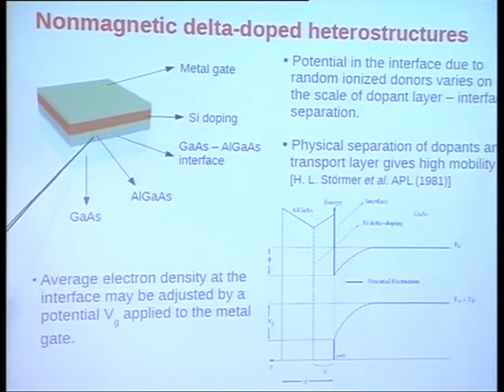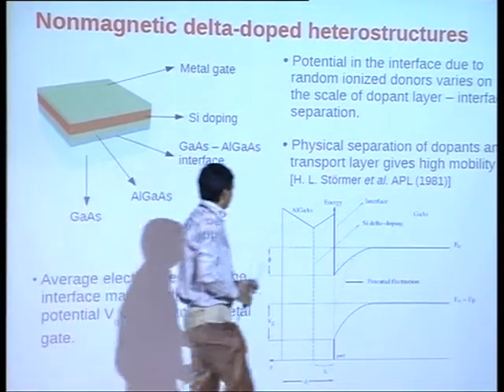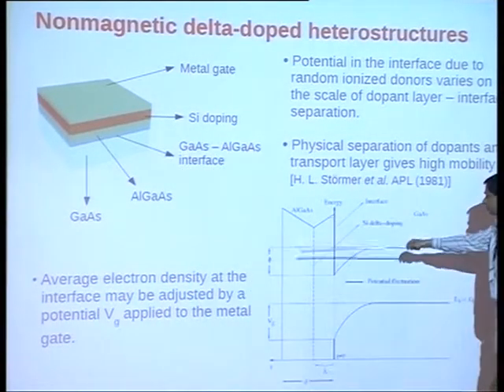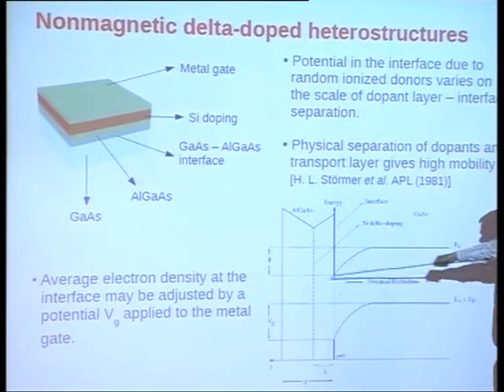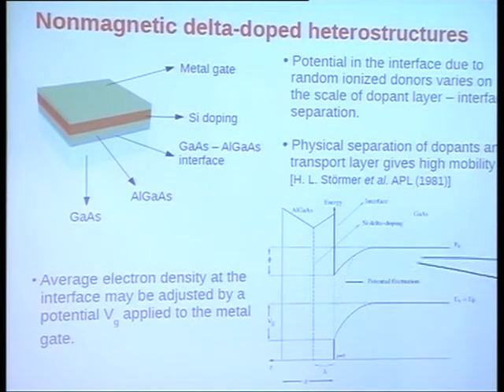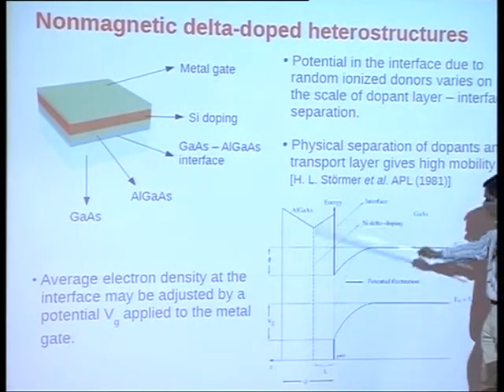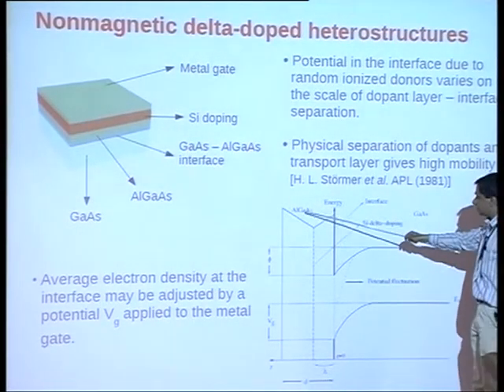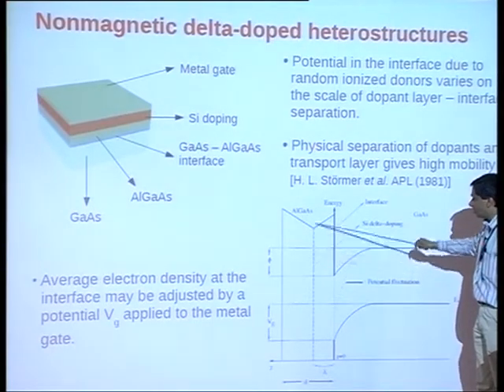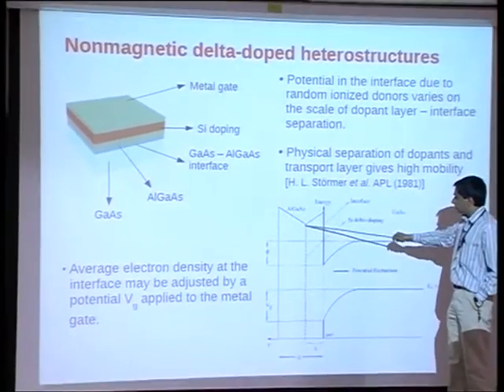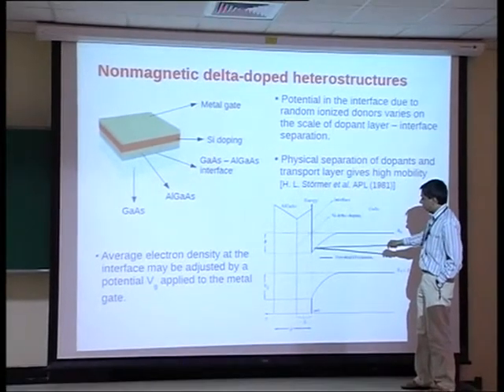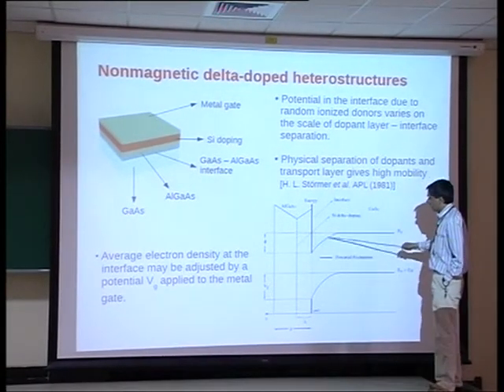Then, at a considerable distance from this layer, you have some donors, silicon for example, and if you make a schematic of how the potential looks as you go into the device in this direction, from the top, you have the conduction and valence bands of gallium arsenide, and this is for aluminium gallium arsenide, and here are the silicon donors. And so the donors lose electrons to this conduction band.